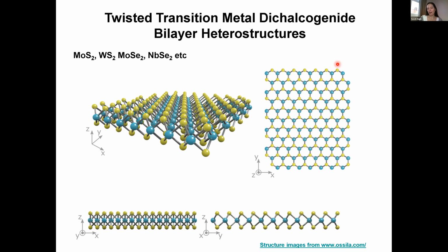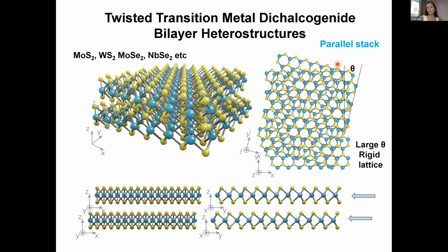And unlike in graphene, we have two different types of lattice that we can produce when we twist a bilayer transition metal dichalcogenide. So if we add the second layer with the same orientation, and what I mean by same orientation, if you look at it in the cross section, as you can see here, we can imagine that the metal chalcogen bond is like an arrow, and if we have the top and the bottom layers pointing in the same direction from the point of view of these metal chalcogen arrows, then we end up with a parallel stacked lattice, and that's what I'm illustrating here.